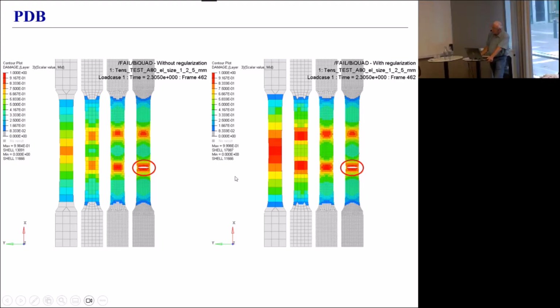You see the initial failure here. With a 1 millimeter mesh, they are simultaneous. It doesn't matter whether you have regularization or not. With regularization, all meshes go almost simultaneously. Without regularization, after the 1 millimeter comes the 2. Quite a bit later comes the 5 millimeter mesh, and finally the 10.